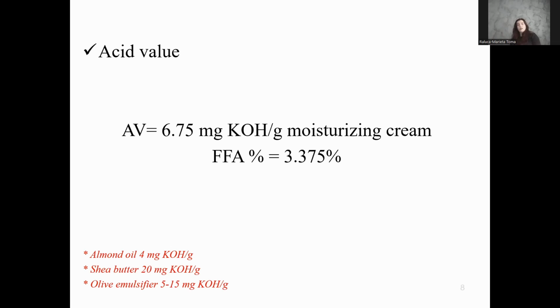For different types of oils, butters, and lipids, we have to analyze experimentally the acid and saponification values. We obtained 6.75 milligrams of potassium hydroxide per gram of moisturizing cream, and free fatty acid content of 3.375%. We don't have any data from the scientific reports to compare with, so we put here just the values from the active ingredients, from the almond oil, from the shea butter, and from the olive emulsifier.